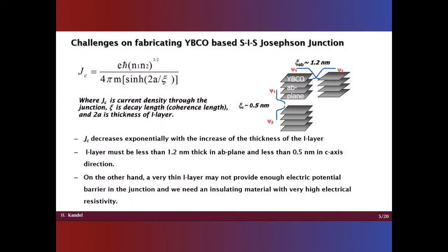The development of a well-controlled and reproducible YBCO-based Josephson junction is very challenging, since in order to provide high critical current, the thickness of the insulating layer must be only about a nanometer thin, which is one billionth of a meter, while maintaining high electrical resistivity. The critical current combined with the normal state resistance of the device make up the ICRN product, or figure of merit of the junction, which directly relates to its efficiency.